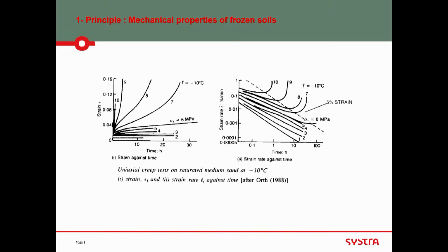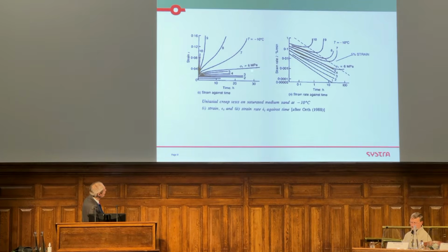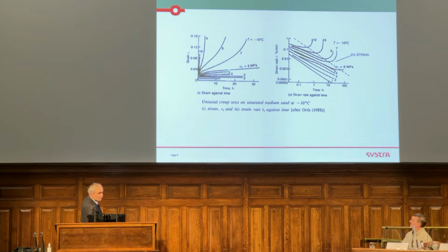This is a diagram where you get in the horizontal axis the time of loading. On the vertical axis, you get the strain of the sample. When you load your sample with 2 MPa of stress, this is how it evolves in strain. It's quite stabilized. You load it at 3 MPa, it's still stabilized. At 6 MPa on this sample, you see that it's stabilized, but it tends to go upward. At 7, it really goes upward. At 8, it goes upward very quickly, 9 and 10, and so on.